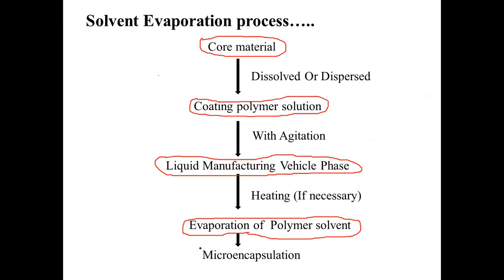So there are various process variables that we have to consider, such as the methods of dispersion forming or temperature cycles, or we can also control the agitation speed. Excess agitation speed will lead to air formation, so there will be problems in the coating. Also the temperature required for the heating, as well as the reduction to ambient temperature, we also have to consider.